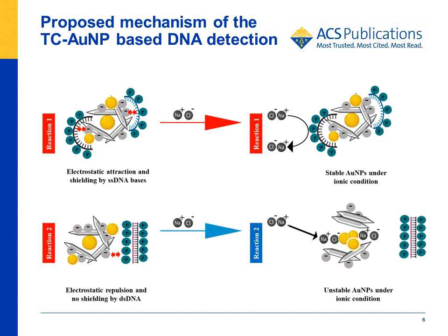In the case of double-stranded DNA, which is the target DNA, all nitrogen bases are bound to their respective units. Therefore, no electrostatic attraction occurred between the nitrogen bases of the double-stranded DNA and charged CNCs, which restricted the formation of DNA protective layer around the TC-AuNPs, and NaCl easily destabilized it, leading to agglomeration and consequently the color change.